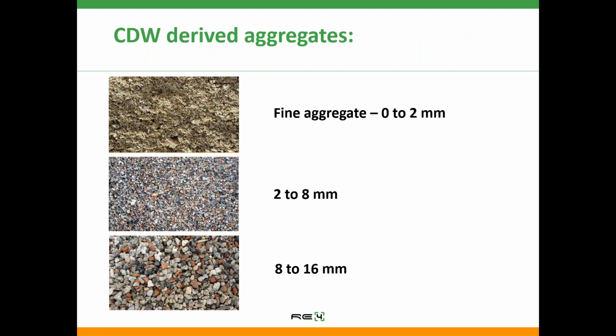So a few pictures showing the aggregates, the fine aggregates, 0 to 2 millimeter, the 2 to 8 millimeter, and the 8 to 16 millimeter. What one can see from these pictures is that the aggregate we have is a mixture of masonry, the red particles, and then we've got the aggregates as well as aggregates covered with cement paste. But because of the separation plants that are being used, developed by CDE Global, the aggregate is relatively clean.